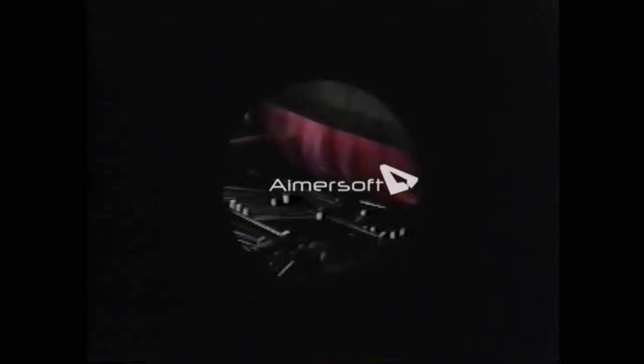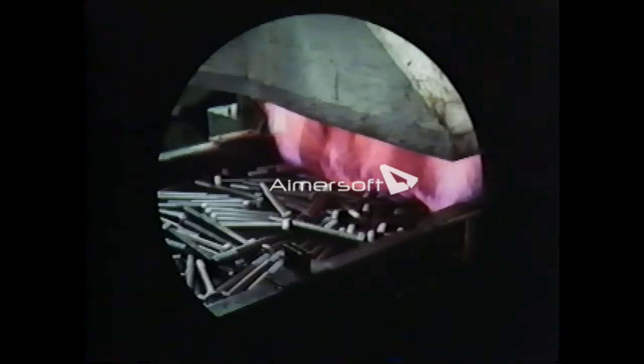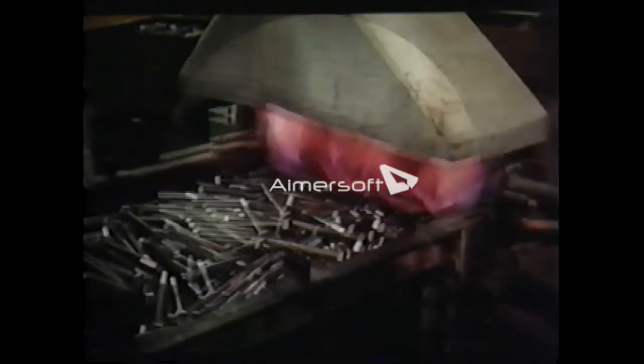Once formed, bolts must be hardened and tempered through heat treatment to create the desired strength level. Like annealing, hardening is done in a controlled atmosphere to prevent carburization or decarburization. Bolts fed onto a furnace belt are soaked in the furnace for approximately 45 minutes.